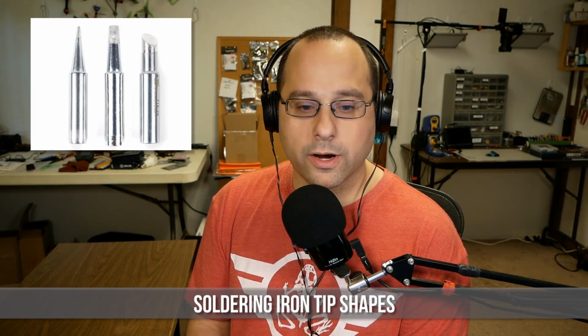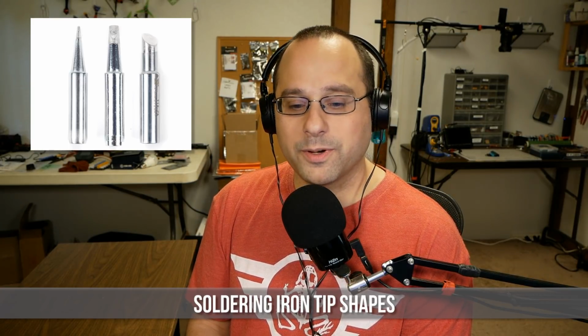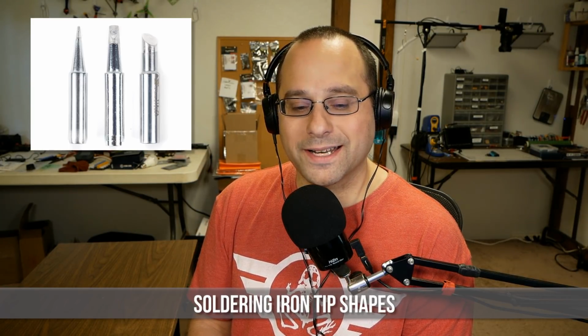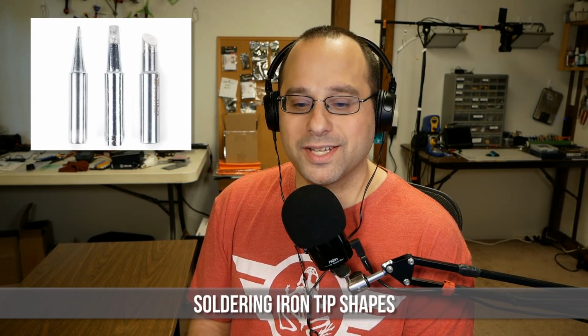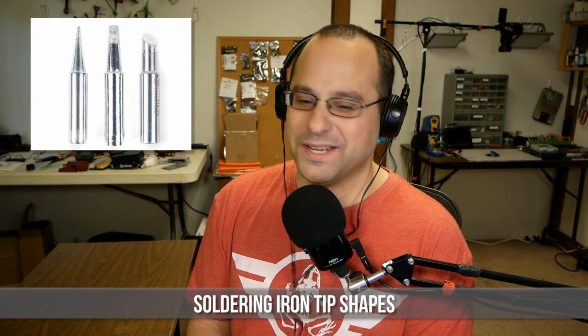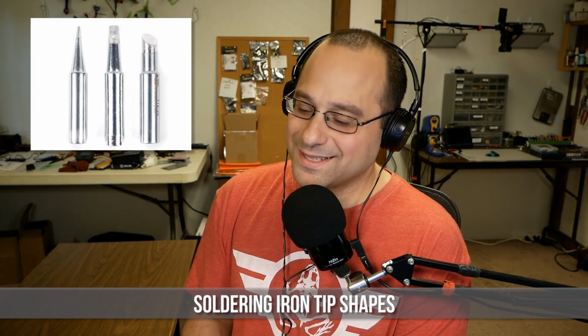Yeah. Way back when I had one of those irons and was struggling, especially with maybe a 12 gauge wire, I would put the heavy bevel tip on it, and then I would just let the iron sit there for 5 minutes and get good and hot, and then I would get in there and do one joint, and then the tip would cool down, but I would just barely finish the joint. Right. So it's not good practice.